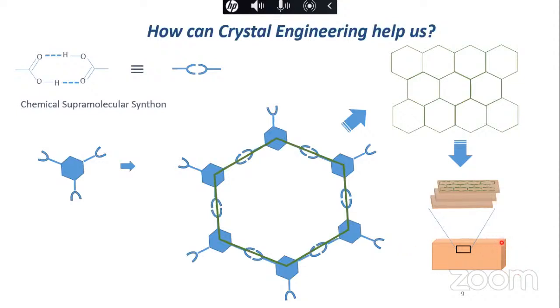Then you will measure the crystal structure, measure the properties of these crystals, and from these properties, you will be able to link them to the underlying crystal structure. For example, if you have layered structures, the mechanical properties from the top and the side will be completely different, and you can explain that based on the crystal structure. So this is how we establish the correlation between the crystal structure and the properties.